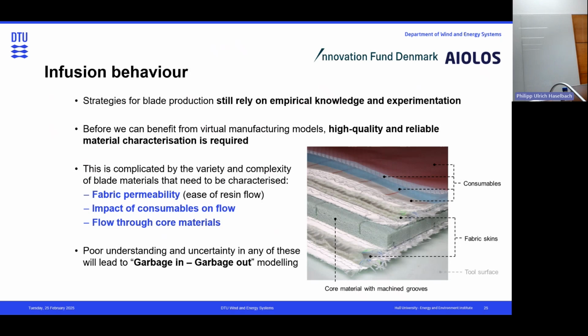So when you do infusion, and I don't know all your backgrounds, but usually you put your dry plies into a mold, and then you have some flow mesh on top that enhances the resin transport during the infusion process. And these are consumables, and they can also have an impact on the flow itself because they have a specific grid, and depending on how the grid is laid up, the resin flows a different way. And all that we analyze as well, and also how the flow goes through core materials.